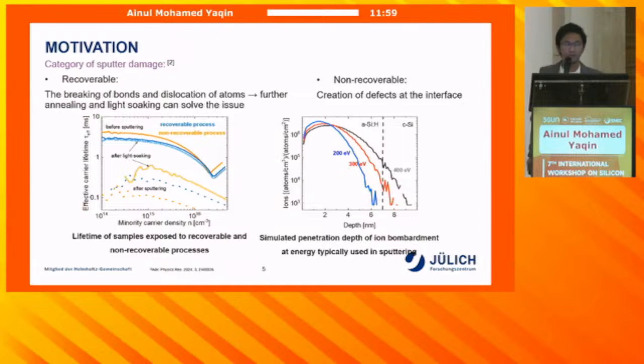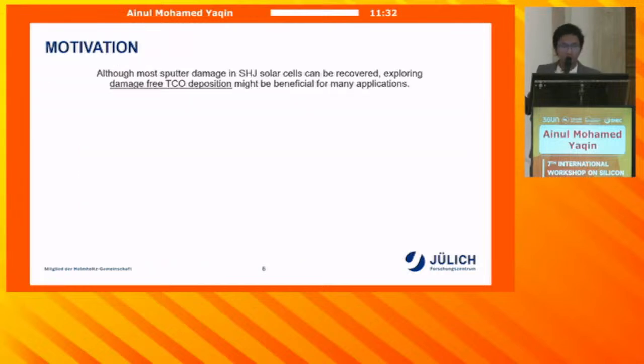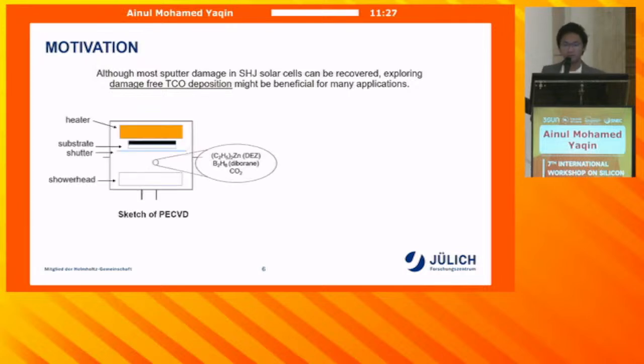For example, in our institute, we did some sputter damage investigations. Here we show the effective carrier lifetime with the sputtering at two different conditions, one being recoverable and one being non-recoverable. We also simulated the ions penetrating into the amorphous silicon, crystalline silicon interface, depending on the energy typically used in the sputtering process. So, although most of the sputter damage in silicon heterojunction solar cells can be recovered, exploring a new damage-free TCO process might be beneficial for many applications.